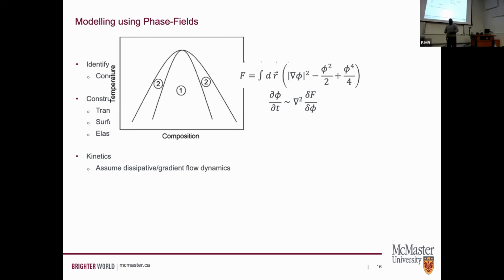And so there, the dynamics, at least if you're a conserved variable, something like concentration or density, follows this Fickian type equation. And in this case, what I've constructed is the simplest phase field model I can that describes spinodal decomposition or phase separation. I've identified essentially two equal wells with this quartic function. That gives me my two phase separated states. And then I've added in the surface term that separates those two separated phases.